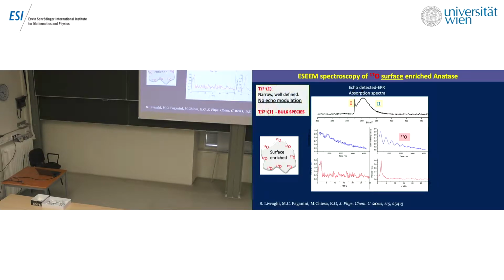So this is the first answer: species 1 is narrow and well-defined, with no echo modulation, so it's a bulk species. And if it is a bulk species, most probably, I will show that, it is the regular site of titanium in titanium dioxide anatase.